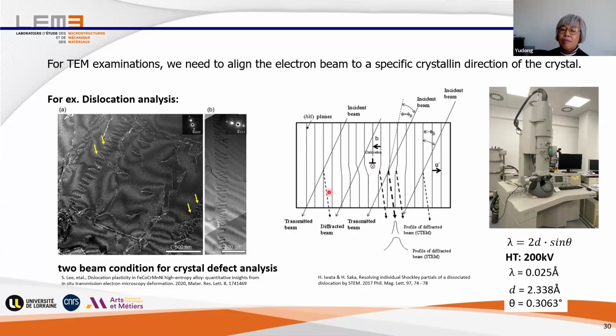And I have to specify that for TEM, we work at very high accelerating voltage of electrons. So the electron beam has a very small wavelength. For example, for aluminum with the 111 plane, with a plane spacing of this distance, according to Bragg's law, the Bragg angle of this plane is less than 1 degree. That means if we align the beam with respect to such a plane, we just make the plane more or less parallel to the beam, then it's okay.